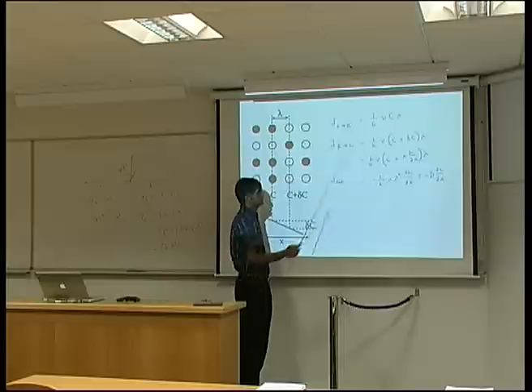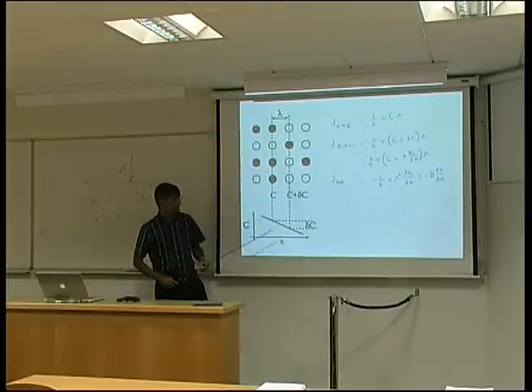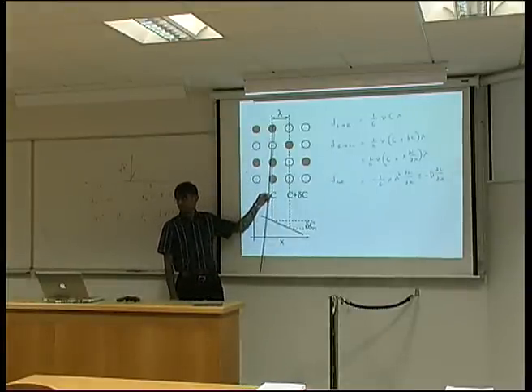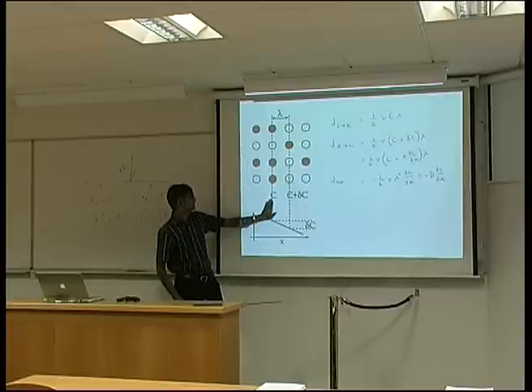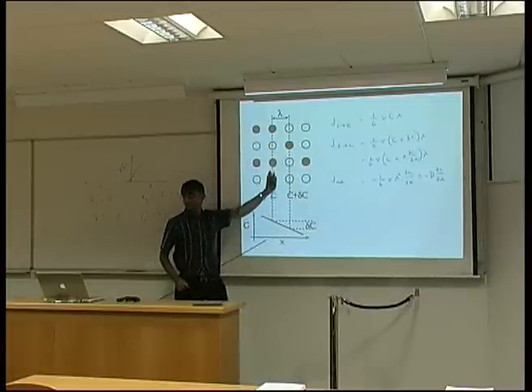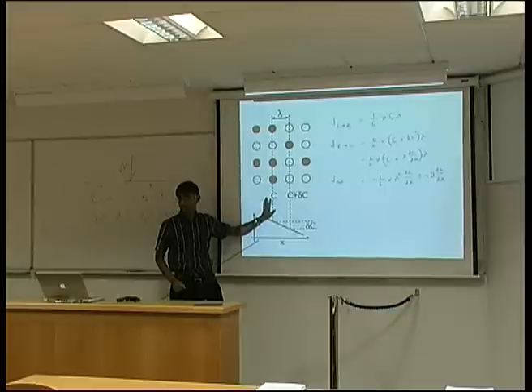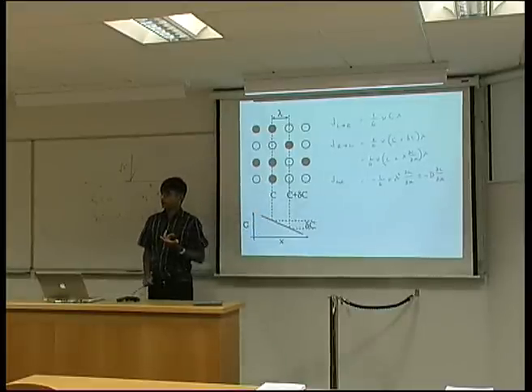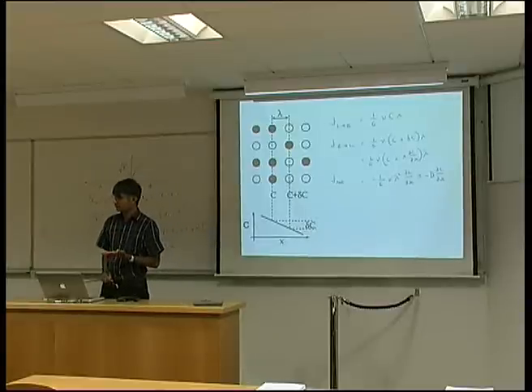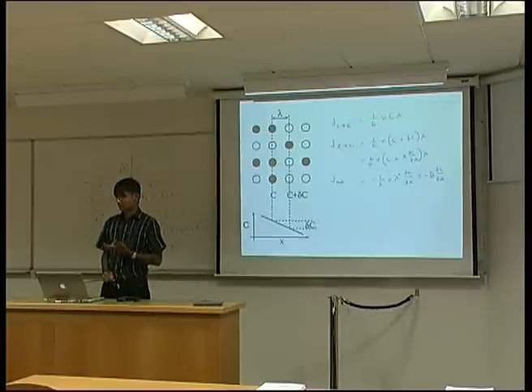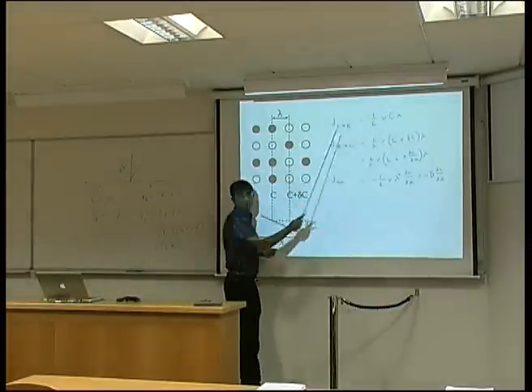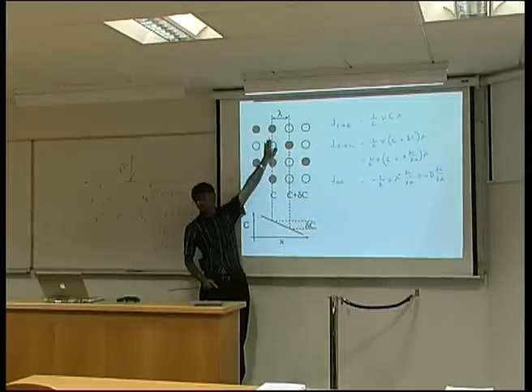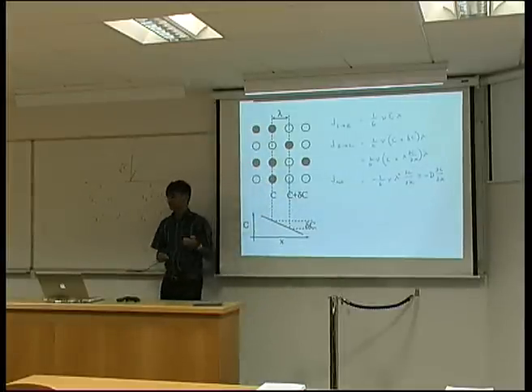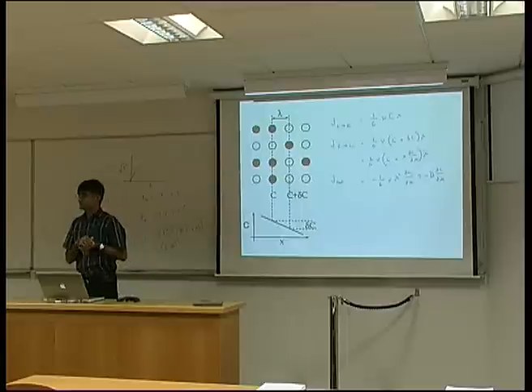Now, the reason why we are multiplying by lambda is that the concentration is the concentration per unit volume, and we want to find the amount of solute we have in this plane. That plane has a thickness lambda, and it has an area of 1, because I said it has a cross-sectional area of 1. So the volume of that plane is simply lambda, isn't it? So concentration times lambda gives you the number of solute atoms that we have in that particular slab of plane. Is that clear to everybody?